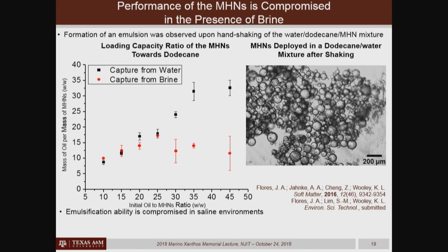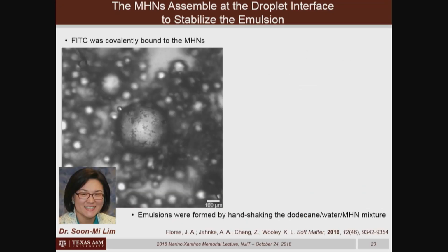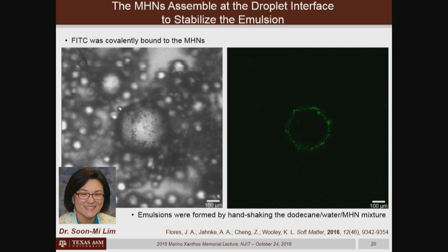And so we wanted to confirm whether these particles were actually acting as particles in the formation of a Pickering emulsion. And Pickering emulsions are quite common for particles, but Jenny's particles are unusual in their shape, right? They're not just a simple particle, they're rather this network of particles. And so what she did was she labeled the particles in order to track where they were residing, and then Soon-Mi Lim performed microscopy measurements and also confocal fluorescence microscopy experiments, and what we confirmed was that the particles are actually at the interface between the oil and the water, so they are acting as Pickering emulsifiers.